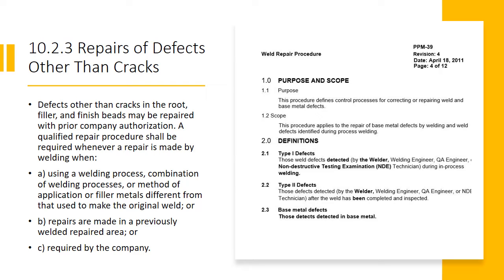Repair of defects other than cracks. Defects other than cracks in the root, filler, and finish beads may be repaired with prior company authorization. A qualified repair procedure shall be required whenever a repair is made by welding, when using a welding process, combination of welding processes, or method of application or filler metal different from that used to make the original weld, or when repairs are made in a previously welded repair area or required by the company. You're probably going to need a repair procedure for most situations.